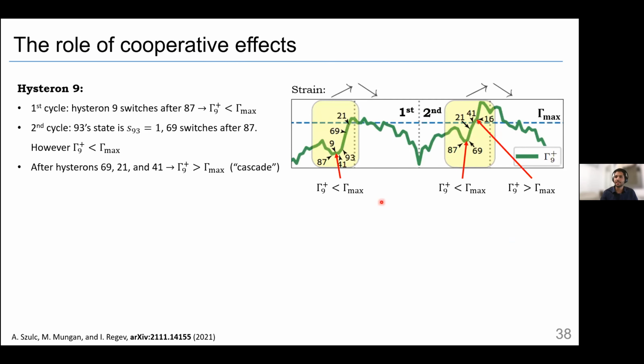But hysteron 9 is the interesting one. If you look at the first cycle, hysteron 9 switches after 87. This is when gamma plus of 9 is below gamma max. In the second cycle, we want to see hysteron 9 after 87. We don't see it, but gamma plus is still below gamma max. So this is a bit strange. You'll see that 69 switches before, then 21 and 41, and only then gamma plus of 9 is above gamma max. We call it the cascade of hysterons that push gamma plus of 9 above gamma max.